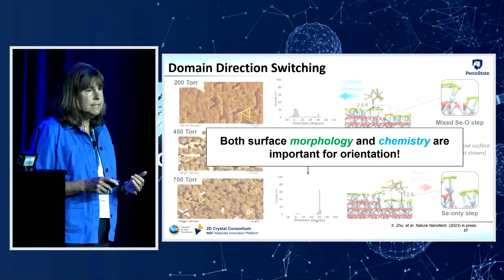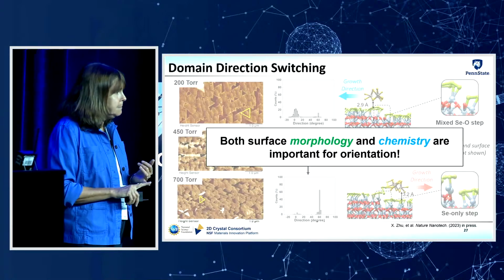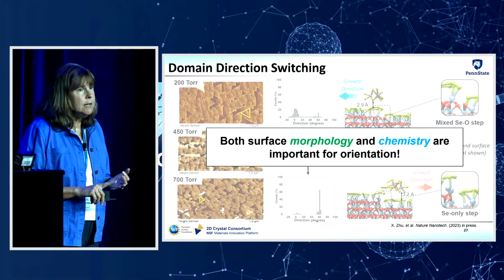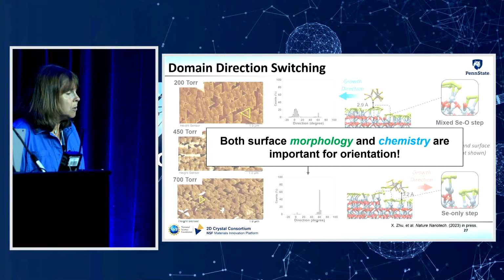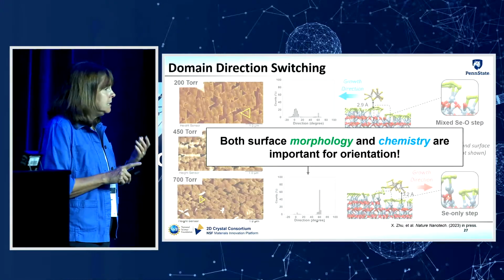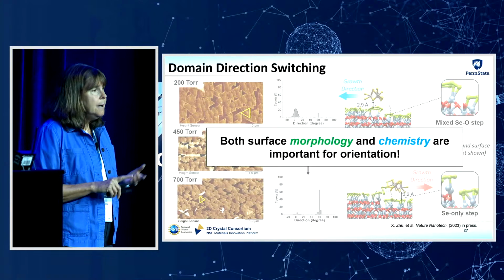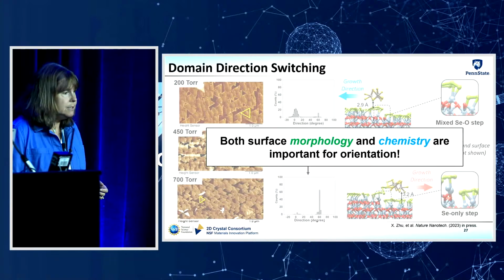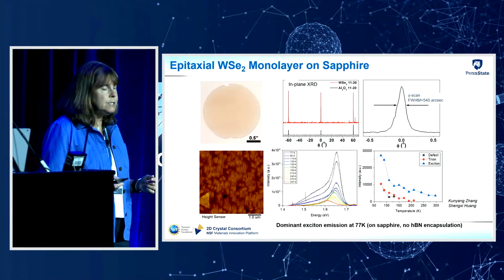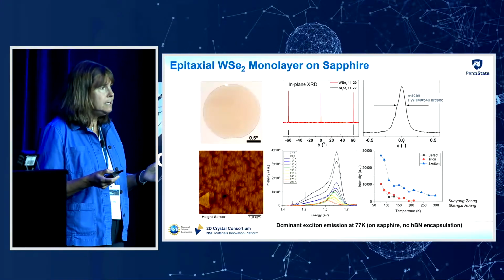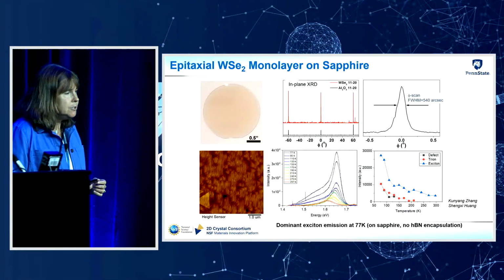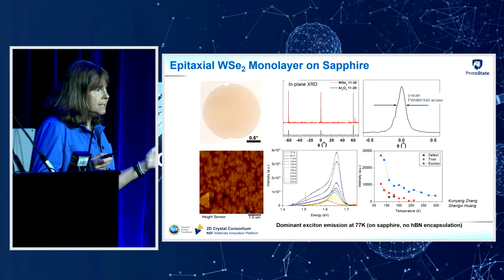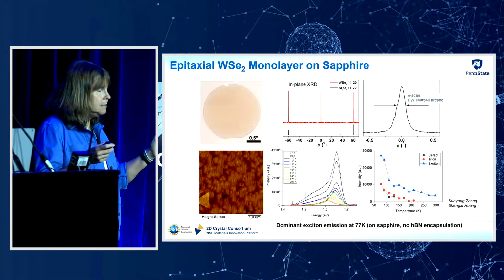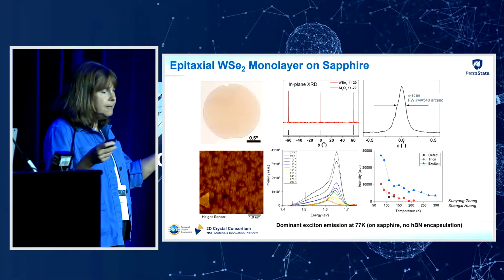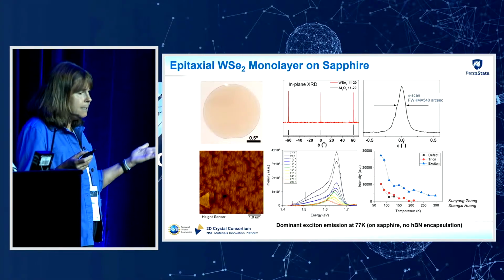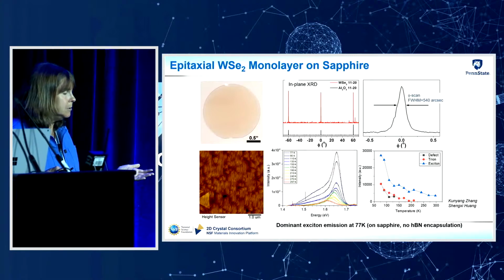So the upshot of this is not only are the presence of steps important, but also the chemistry of the sapphire surface is also very important. And that's going to vary depending on the type of growth technique that you're using and also the particular conditions that you're using. So now let me just switch and tell you a little bit about the properties of our TMD monolayers. So if we extend the lateral growth time out, we can coalesce all these domains and we can get a nearly fully coalesced monolayer across substrates that are 2 inches in diameter.